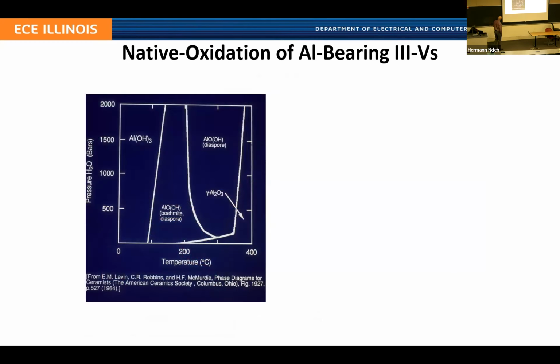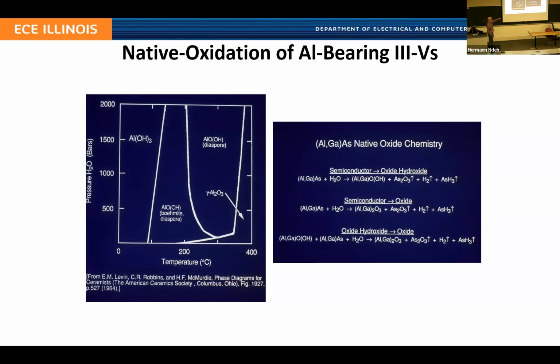What was happening at room temperature is that the aluminum was degrading by formation of aluminum trihydroxides, and that effectively led to etching and decomposition of the material. By raising the temperature, we're able to cross into the phase diagram to form both aluminum oxide hydroxides and aluminum oxide, Al2O3, which are much more stable forms of the oxide. And again, you see some of the chemistry for the formation of the semiconductor oxide hydroxide, as well as Al2O3. Because you have a mixed aluminum gallium alloy, you can form a mixed aluminum gallium oxide system as well.